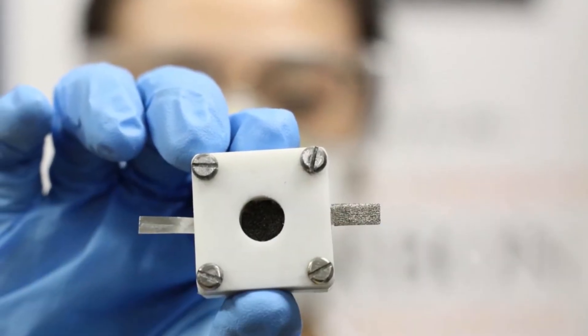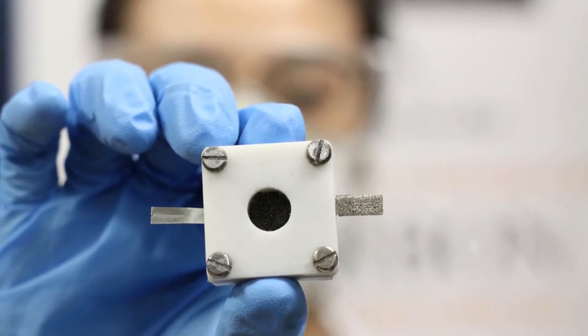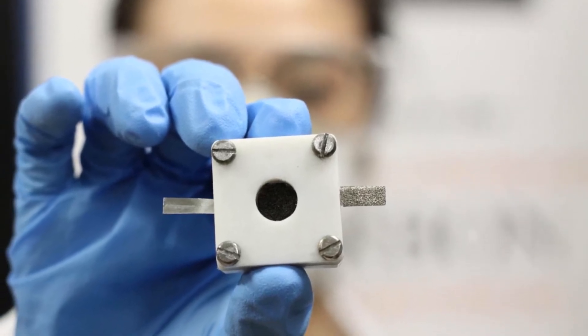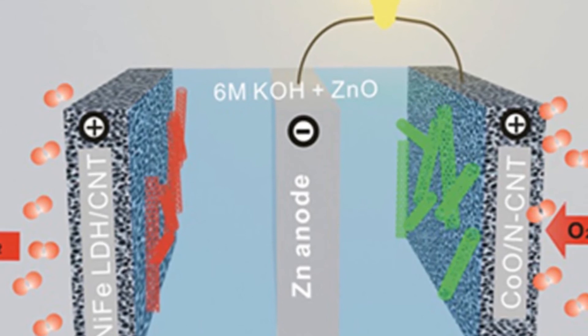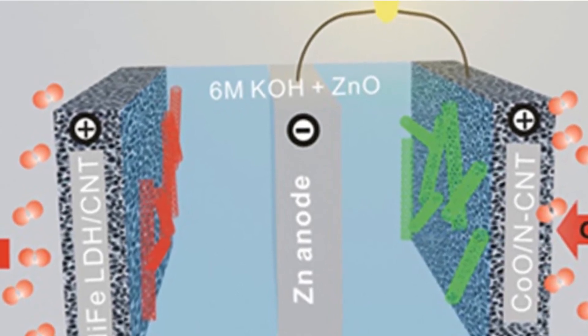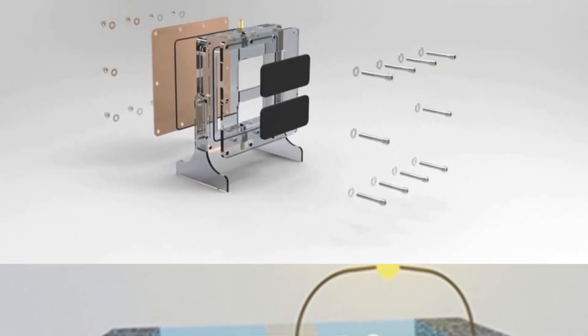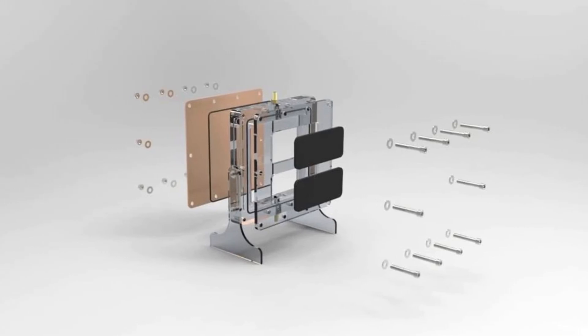Paper co-author Dr. Lee Wei, also from the University's Faculty of Engineering and Information Technologies, said trials of zinc air batteries developed with the new catalysts had demonstrated excellent rechargeability, including less than a 10% battery efficacy drop over 60 discharging, charging cycles of 120 hours.